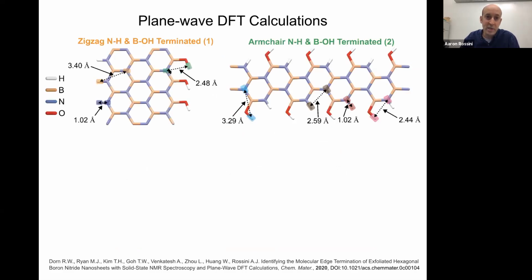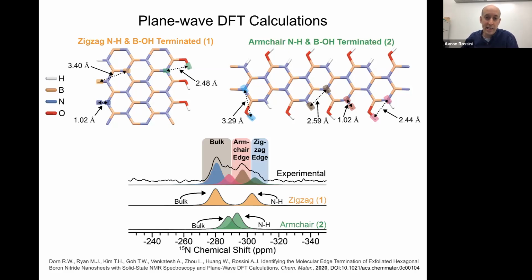To help us interpret that spectrum and understand what those different peaks come from, my student Rick Dorn, who led this work on the hexagonal boron nitride, made plane wave DFT models of the edge terminations of the hexagonal boron nitride nanosheets. He made a model with zigzag edge terminations where you have amine groups on one side, and then you have hydroxyl groups attached to boron atoms on the other side. And then he also made an armchair edge termination model where you can have nitrogens that are terminated with amine groups, or you're going to have borons that are bonded to hydroxyl groups. So if we calculate the 15N chemical shifts using these two models, we can really accurately reproduce the observed chemical shifts. So we can see that the zigzag model gives us these bulk-like atoms.